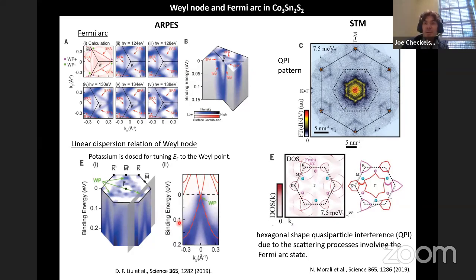this linear dispersion. And I think it was an open question in the community because for these Weyl systems, it took several years. There was a deep appreciation that the magnetic system should exist, but it took several more years for the magnetic systems to be demonstrated from spectroscopy compared to the inversion breaking systems. And there was a lot of thought about, is that because of the finite size of magnetic domains? And to be honest, I think it just took finding the right material and really doing these high resolution experiments to now definitively show that these Weyl states really exist in this system and others at this point.